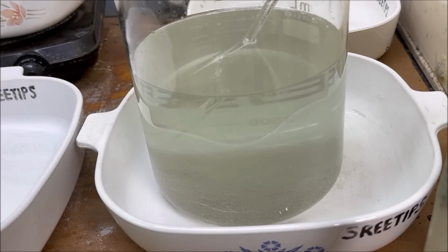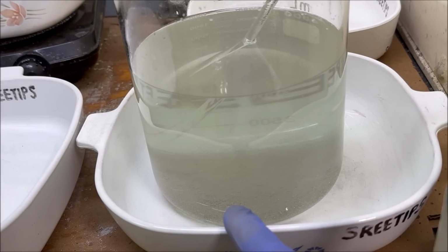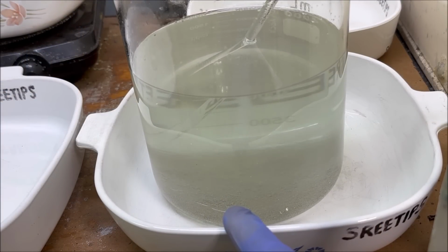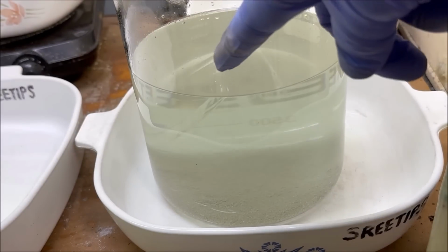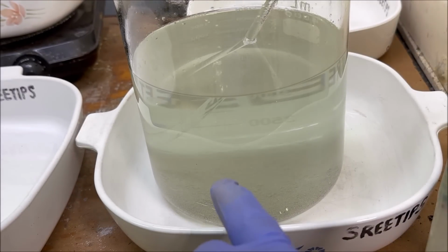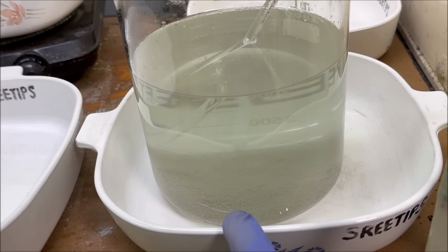It's important to notice that there's still some silver down on the bottom of this beaker that has not dissolved. Yet while it was boiling, there were no fumes up here, which indicates that all the available free nitric acid has been consumed by the reaction.